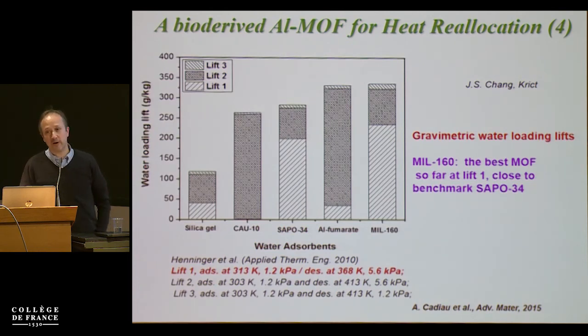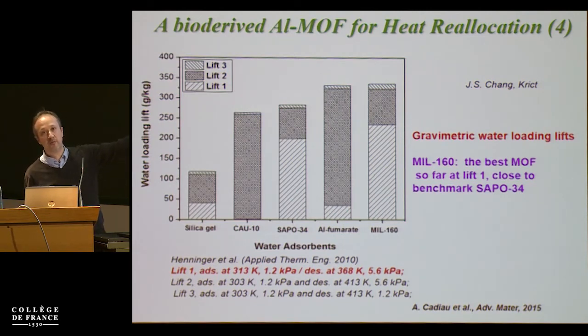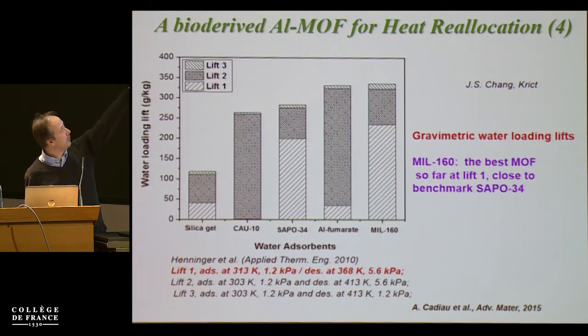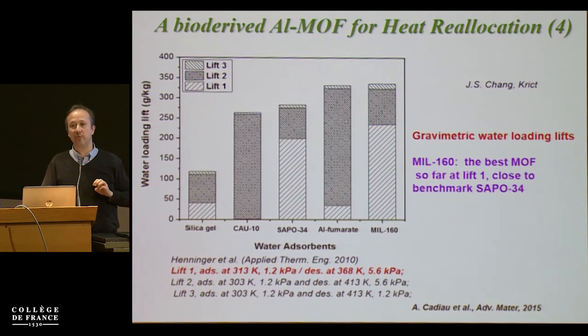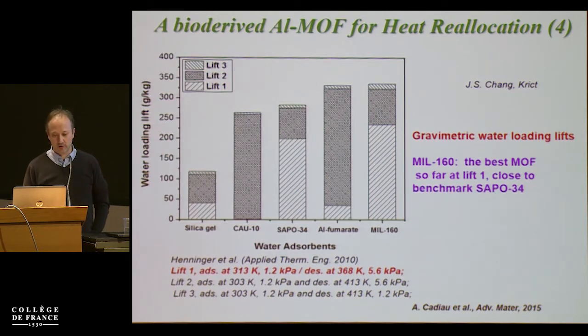Comparing MIL-160 performance with benchmark materials — other MOFs, silica gel, and SAPO-34 — across three types of conditions (LIFT 1 heat pump, LIFT 2, LIFT 3), MIL-160 shows almost the same performance as, or slightly higher than, the commercial sorbent SAPO-34 under heat pump conditions. This does not mean it will replace SAPO-34, but it demonstrates that a MOF material can be as efficient as commercial inorganic sorbents.